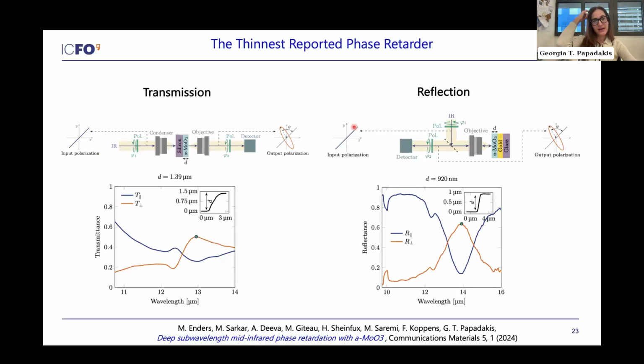So we actually went ahead and built these devices and we characterized them in transmission and in reflection mode. And you can see here, for example, that coming with parallel and orthogonal polarization, which refers to just orthogonal or parallel to one of the axes of the material, you can see that within the Reststrahlen band that I showed before, the polarization totally flips, which is exactly the definition of a half-wave plate.